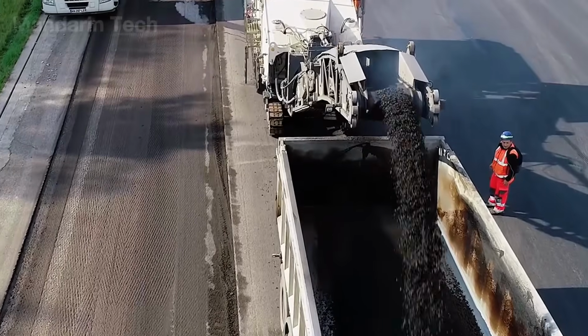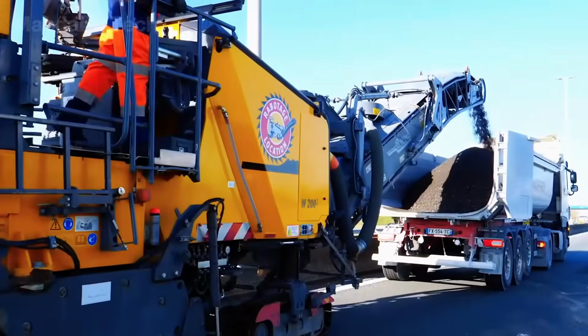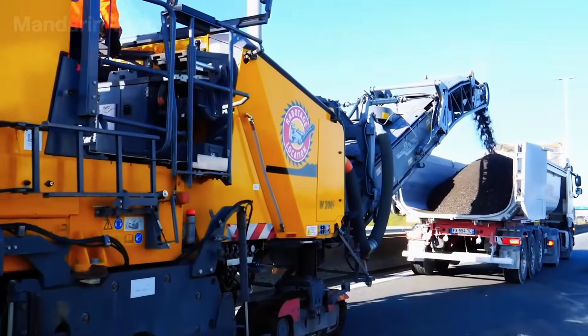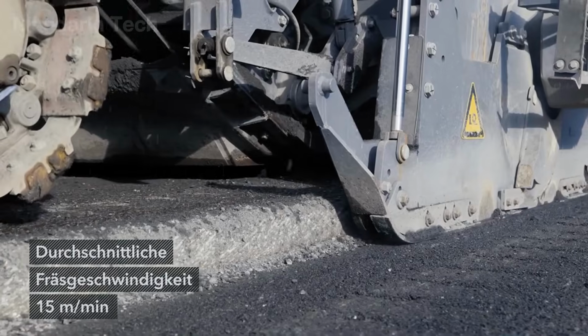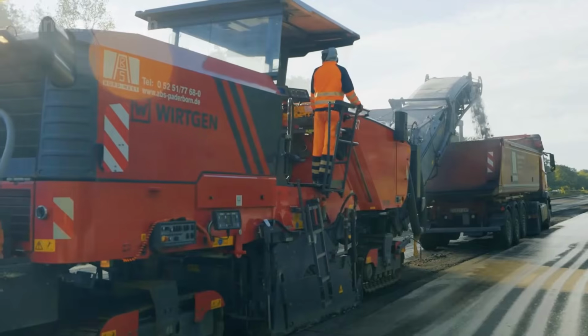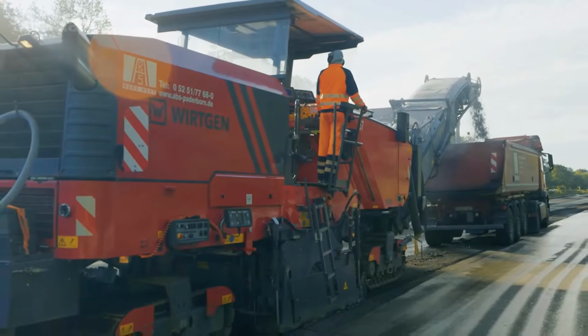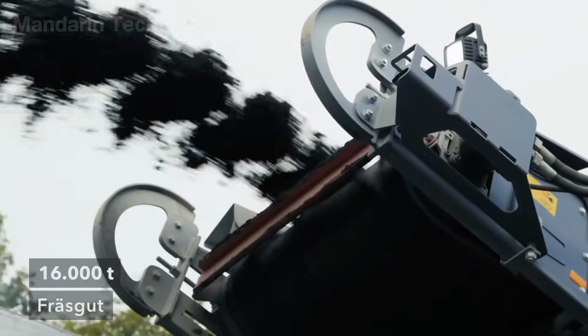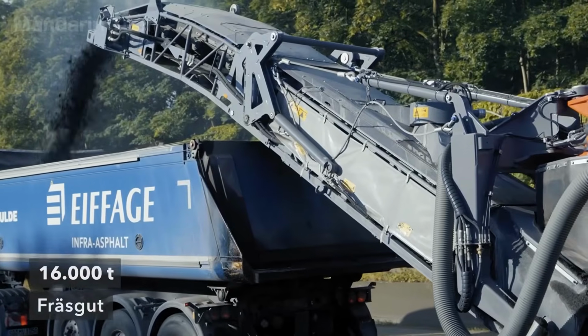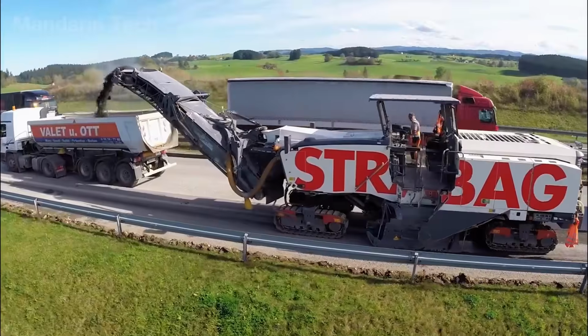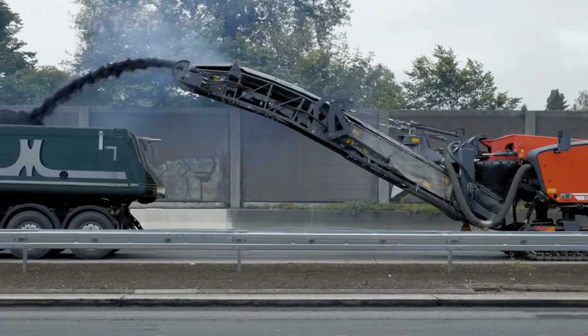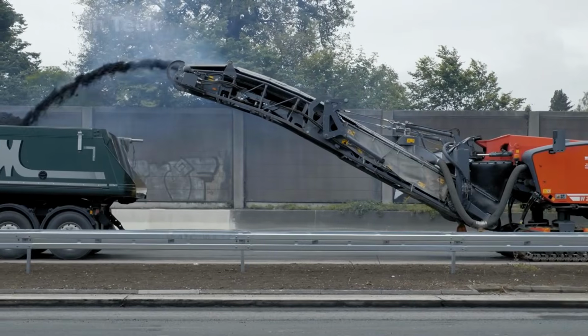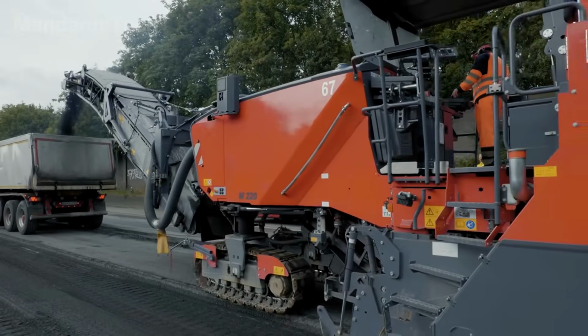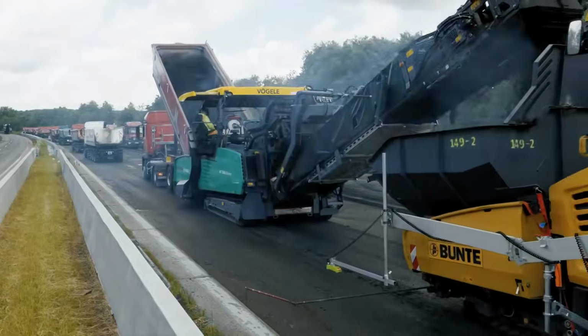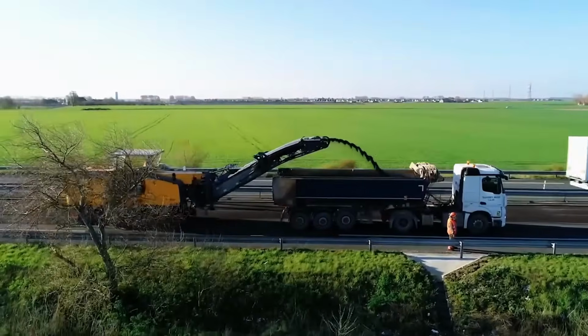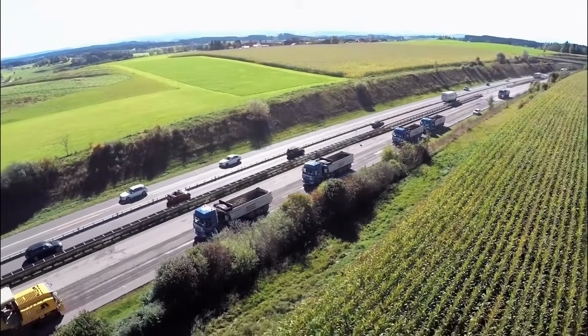The first step in this resurfacing process is milling off the old asphalt layer, usually between 2 and 10 centimeters deep depending on the level of damage. The machine grinds the old asphalt into small pieces, collects it onto a conveyor belt, and loads it directly into the truck behind. Milling removes only the worn-out top layer while keeping the underlying base and structure intact. This way, the road doesn't have to be rebuilt from scratch, which reduces cost and significantly shortens construction time.